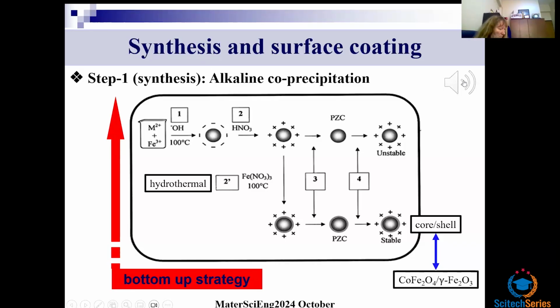The core is the preserved structure of the cobalt ferrite, and the shell is actually an iron oxide, mostly maghemite. And then we can take, increasing the pH, we can go through the point of zero charge, and then lower the pH again. We come finally with a very stable core-shell structure, and the core is the cobalt ferrite phase, and the shell is the maghemite phase.